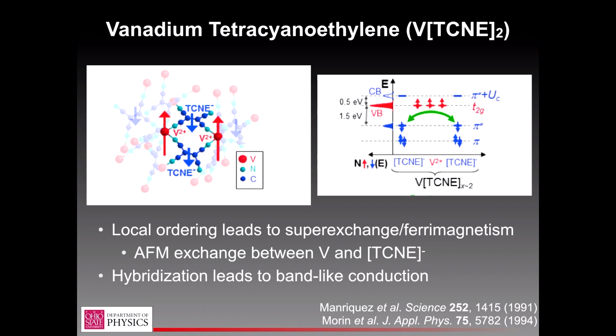In addition to making an electrical connection here as an organic semiconductor, allowing hopping transport throughout the material, you also have an exchange interaction whereby the vanadium, which starts off with 5 electrons, donates 2 charges to the neighboring TCNE, giving them a negative charge and an excess moment. So then you end up with antiferromagnetic ordering locally between a TCNE and a vanadium, or ferromagnetic ordering globally. So this is a compensated or imperfectly compensated antiferromagnet. So you have some remnant moment.